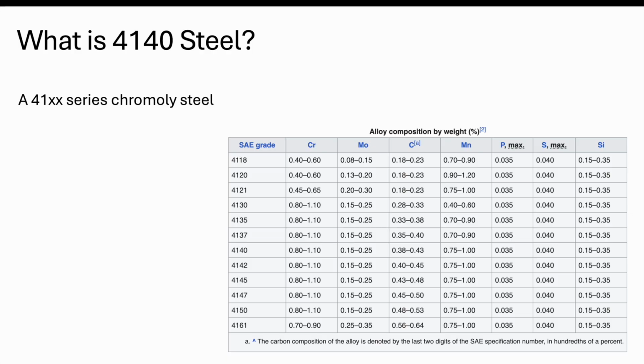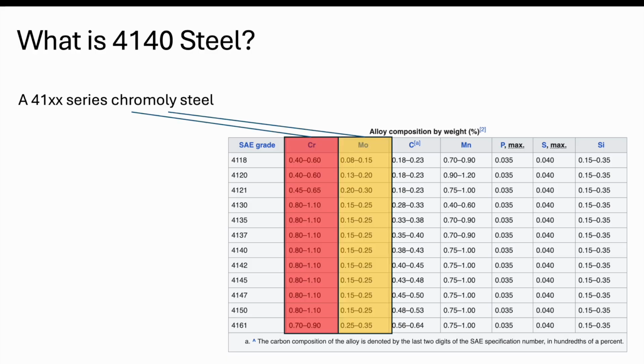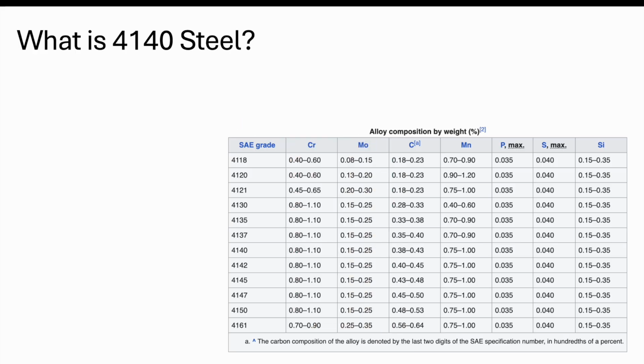And the 4100 series refers to what we call a chrome moly or chromium molybdenum steel. So both of those are added to the steel alloy on top of the iron and carbon. Here you can see that there's some variations, but we've got between a half and a whole percent of chromium and between 0.1 and 0.4 weight percent molybdenum, or moly. So that's why we call it a chrome moly steel.